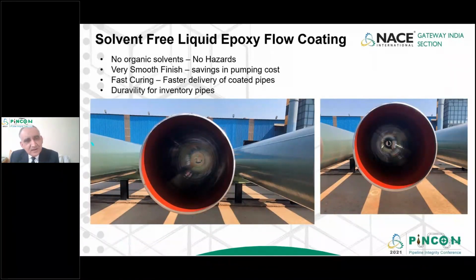Now here are some pictures where a new technology is being used in terms of flow coating. It's a solvent-free product, 100% volume solid. No solvent is used. This product gives a very smooth surface, very safe, no fire hazard, no discomfort to the applicator because there are no fumes of hydrocarbon solvent. The product gets applied very smoothly and the glossiness is high. The product cures very fast. Typically, available products in the market are like 50% volume solid products, which take 5 days to cure, 7 days to cure. This product can cure within 5 to 6 hours.